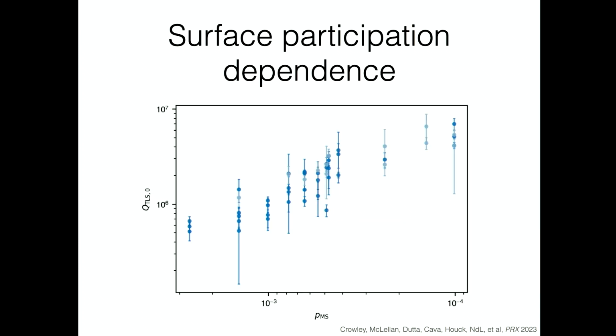And what we see is that as advertised, as we make the devices bigger, so this is to zeroth order sort of like the pitch between these devices, the Qs go up. And this isn't just Q, this is the linear absorption due to two-level systems. So we decrease the two-level system component as we get them bigger. But then maybe they're starting to saturate at the biggest devices, so we don't keep on increasing.